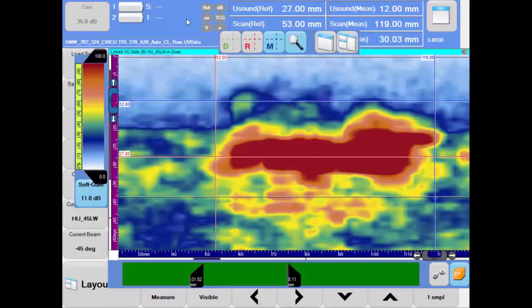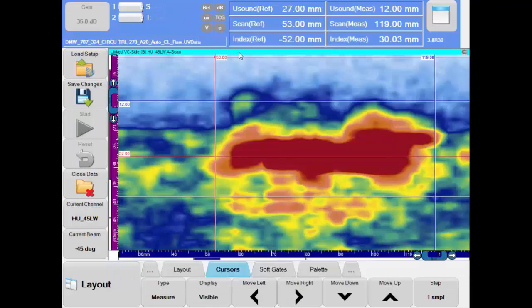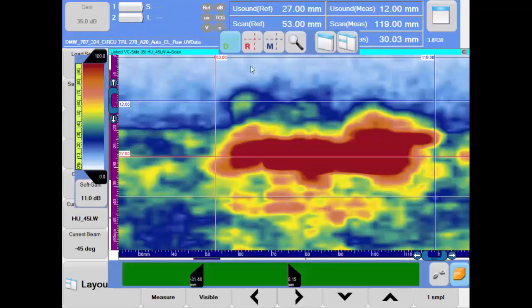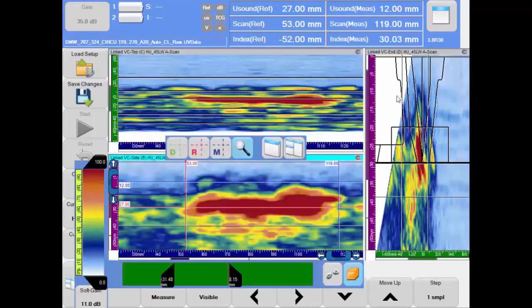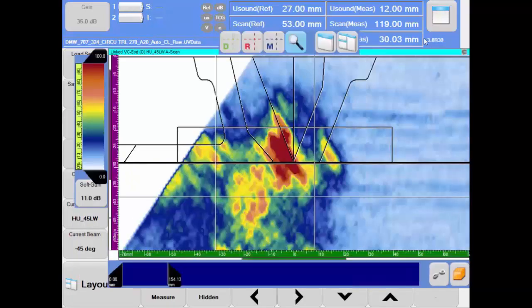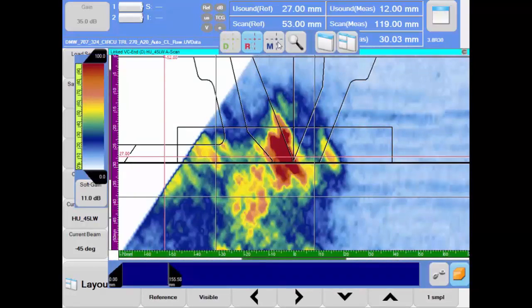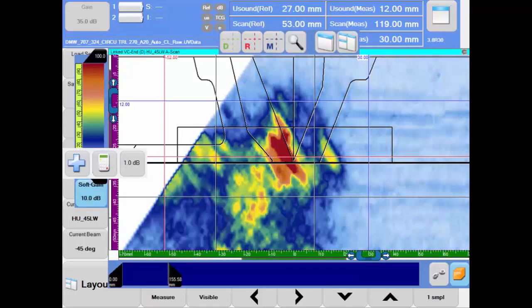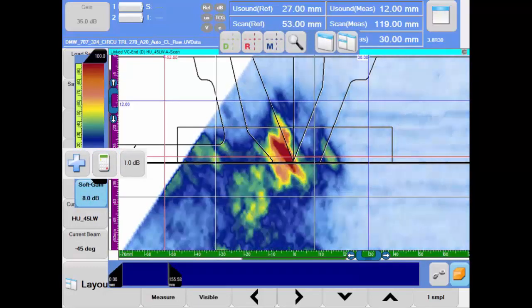Obviously, the tip diffraction technique cannot always be used successfully. For very small cracks, the corner trap will obscure the close by and weaker diffraction signals. Ideally, an experimental validation exercise on a representative welded specimen with EDM notches should be used to determine the lower limit of the cracks that can be reliably sized. As such, the absence of a resolved tip signal can be a good indication for a very small crack.